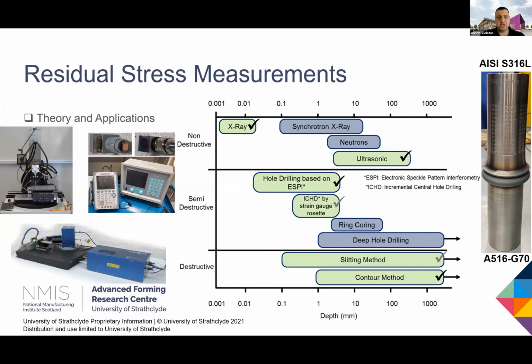So the characterization work continued with a measurement of residual stresses. As Laurie mentioned earlier in her slides, we offer in the FRC quite a range of different techniques depending on what we want to measure. We have X-ray diffraction, laboratory X-ray obviously for surface stresses. We have hole drilling equipment for surface and subsurface. We offer two different techniques, one with electronic speckle pattern interferometry, which allows us to use the specimen as is, and one obviously with strain gauges. And then we have some more destructive techniques like the slitting method and the contour method, which are fully destructive, but they give us much more information, particularly for the bulk material.